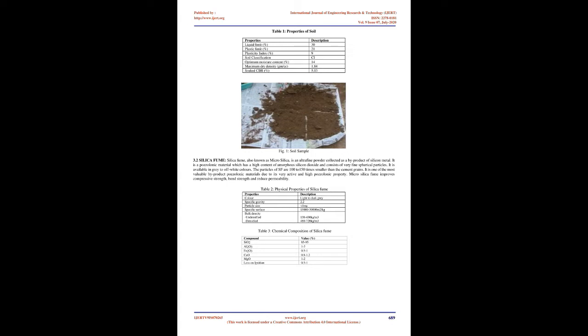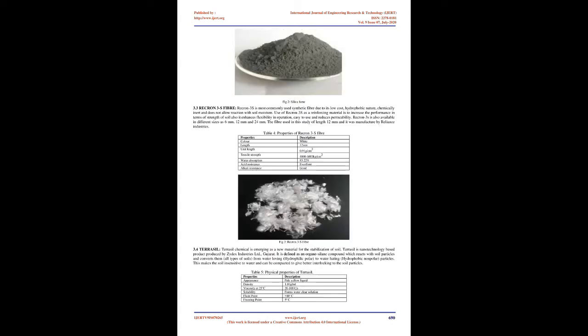Rinta Johnson, Dr. Koti Rangaswamy, 2015. The soil was collected from Kunamangalam area of Calicut district in Kerala and the Terrasil nanochemical was collected from Zydex Industries Limited for the stabilization studies. Experimental program was carried out on both clay and cement treated clay treated with different dosages of Terrasil. Specimens were prepared with 0.05%, 0.07%, and 0.09% Terrasil and 1% cement by weight of soil. Results obtained were compared and studied. The CBR strength of soil mixed with optimum dosage of 0.07% Terrasil chemical is improved about 6 times the CBR strength of clay soil. The treated soil was found to be impermeable.